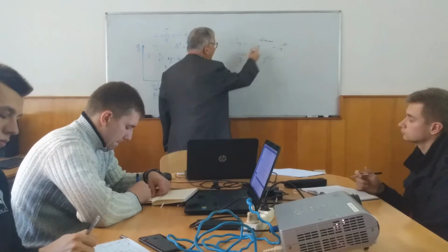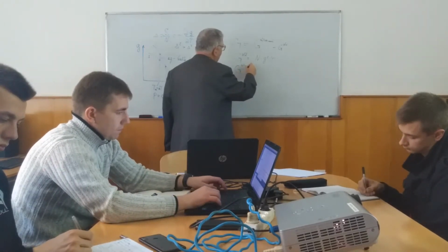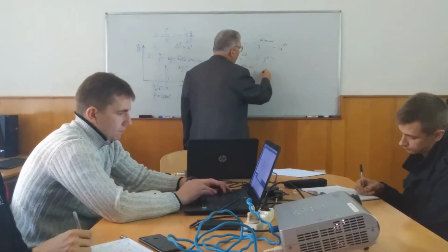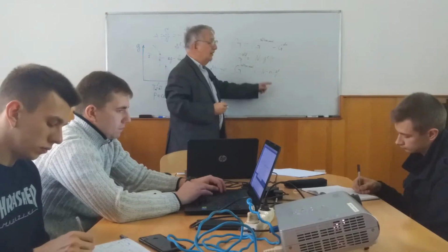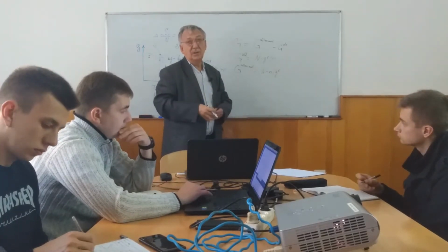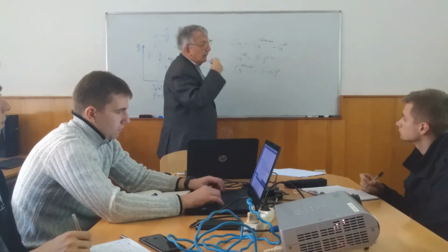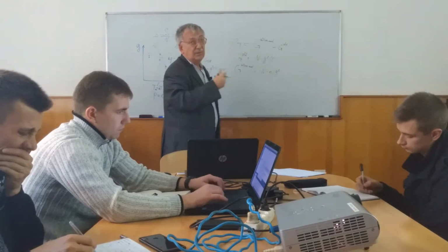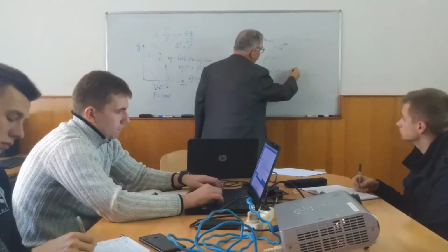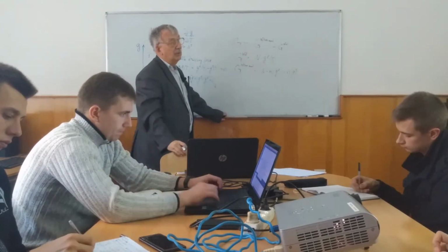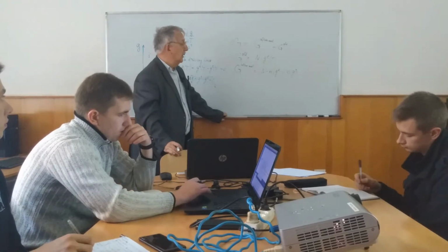So what is G new? G after nucleation is N capital minus N small multiplied by GL. N small is a number of atoms which were organized in the new structure in crystal. So N capital minus N small is a number of atoms in the old phase which still coexists with the new phase, plus N small multiplied by GS. N small is a number of atoms belonging to the new phase, to the nucleus of the new phase. GS is a bulk Gibbs free energy per atom in this new crystalline phase.